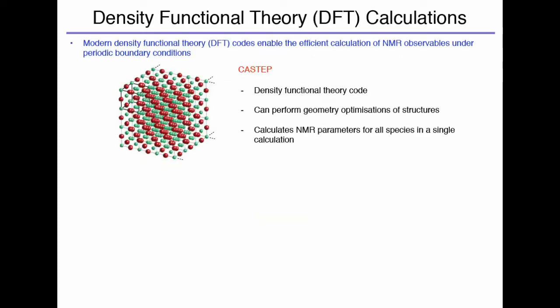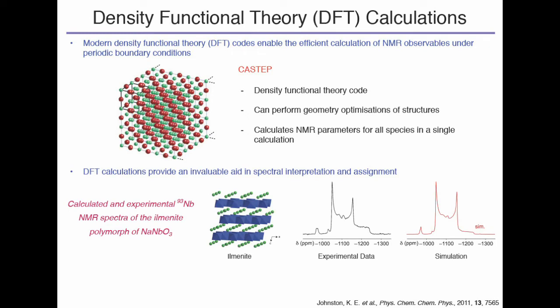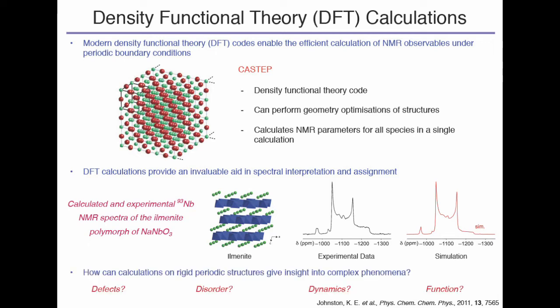Okay, so increasingly in NMR, what we need is a way of validating our experimental observations. So one thing we can do is use quantum chemical calculations to calculate the NMR observable. So we can almost predict the answer before we've made the material and run the experiment. And that's really, really good because it narrows down how you experiment. So DFT calculations are really useful for helping us to interpret and assign data, but also, much more than that, they can give us information on defects, disordering, any dynamics, so if you've got movement, and even in some cases the functionality of a material. So lots of information can be obtained from these.